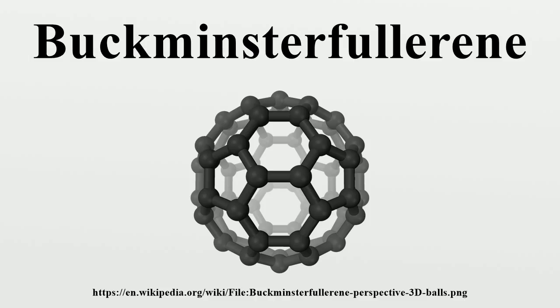The C60 molecule is extremely stable, withstanding high temperatures and high pressures. The exposed surface of the structure can selectively react with other species while maintaining the spherical geometry. Atoms and small molecules can be trapped within the molecule without reacting. C60 undergoes 6 reversible, 1 electron reductions to C60 6-, but oxidation is irreversible. The first reduction needs ~1.0 V, showing that C60 is a moderately effective electron acceptor.